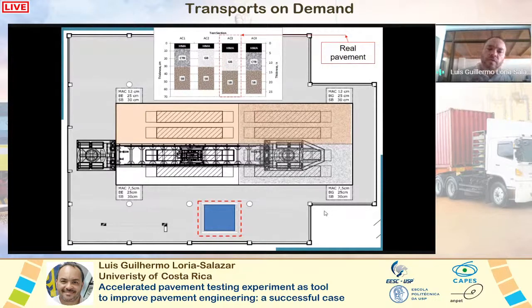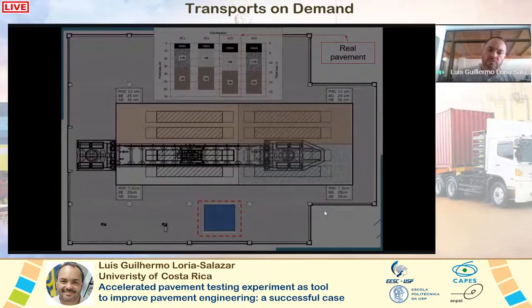We also use a cemented base and a granular base of 25 centimeters, and a subbase of 30 centimeters. We have 2 repetitions in each test track, but the idea was to use one dry and the other wet, under fully saturated conditions for the subgrade. At the bottom of the slide, you can see our saturation chamber that was used to simulate the water level at the subgrade, or wherever we want to place it.